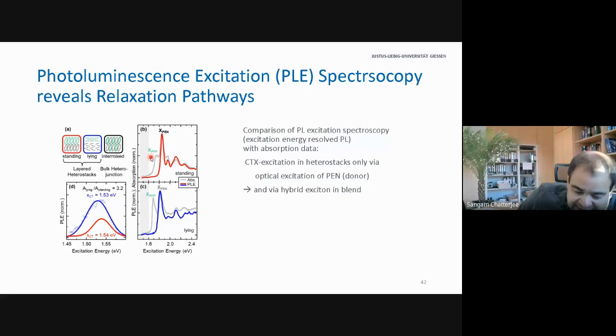And to understand this, we did photoluminescence excitation spectroscopy. What is photoluminescence excitation spectroscopy? You look at the detection channel at very low energies, which is this gray highlighted area, and you scan your excitation light source across different energies. This way, you quantify how much light you get out depending on what you excite. And for reference, I've shown the linear absorption of these molecules or molecular crystals or structures in gray. And on the naive side, this charge transfer state, or whatever that might be, only seems to be populated from the pentacene and not the perfluorinated pentacene. Too bad, as we spent so much time studying the perfluorinated pentacene, but it doesn't seem to contribute.